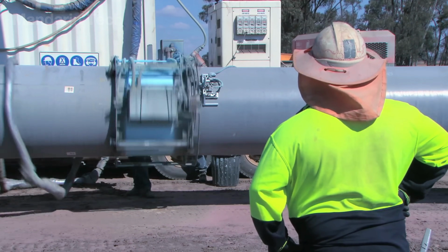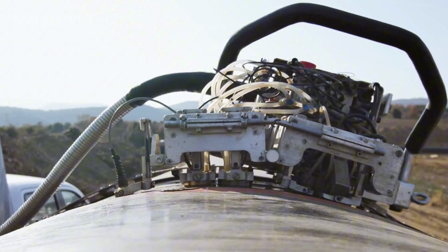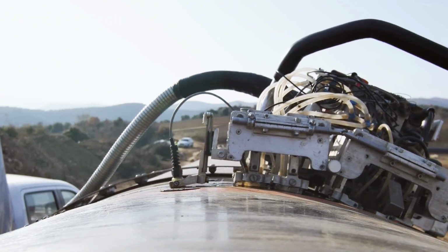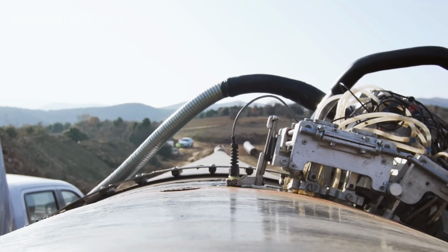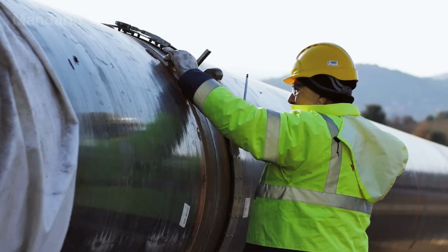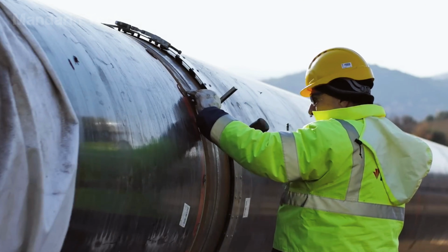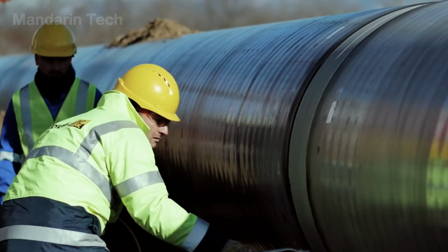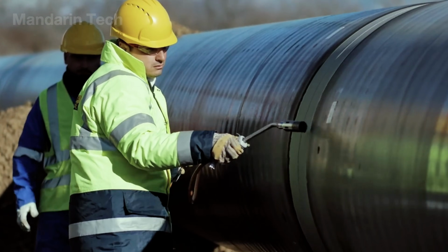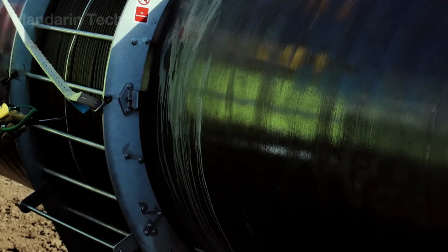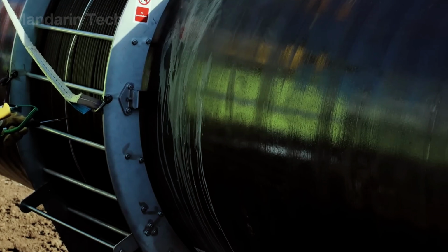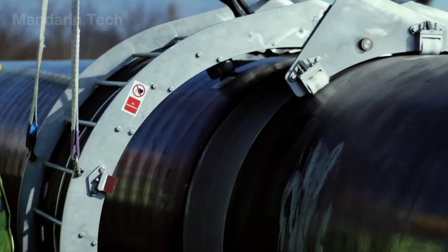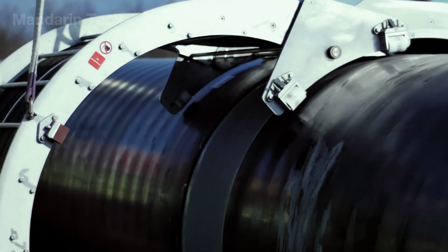After welding is completed, each joint is subjected to automated ultrasonic testing to verify the absence of internal flaws. The field joint coating team then carries out abrasive blasting to prepare the surface and applies a multi-component liquid epoxy coating, creating a durable, fully sealed protective layer before the pipes are finally lowered into the trench and backfilled.